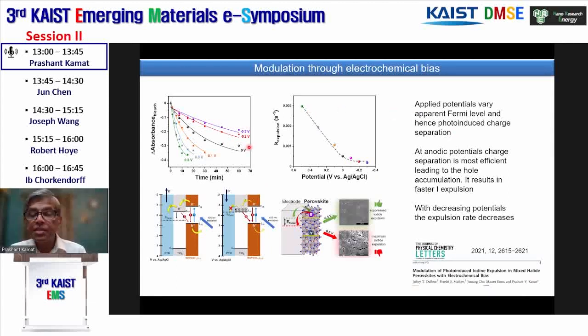oxidized. We can also modulate this expulsion of iodine by controlling the bias. So this is a case where you make it more positive potential bias, and the electrons are taken away more efficiently, leaving more accumulation that leads to the oxidation of iodide. And you can see here the dependence between minus 0.3 and plus 0.5. At these potentials, there is no change in the chemistry of this halide as such. It only happens when you shine the light, this iodide comes out. Otherwise, it is stable in these potentials.